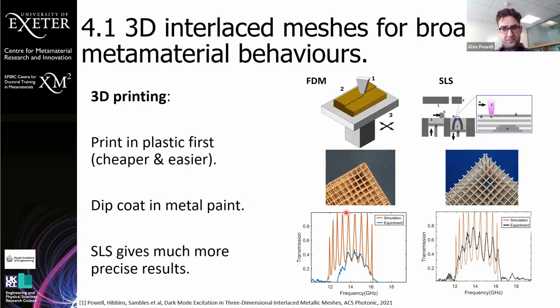So we tried making some of these meshes. First of all, we started with a single mesh, because no one had really investigated these, a 3D printed single mesh in terms of microwave transmission. We thought that'd be a nice experiment to start with. We tried a few different ways of 3D printing this. Firstly, we used classic 3D printing, fused deposition modeling, where you have filament extrusion. That worked, but it's pretty gross, to be honest. You can visibly see that the cells are not very even. There's a lot of surface roughness, and that results in a lot of loss when you try to measure the transmission through it. So that worked, but wasn't great.